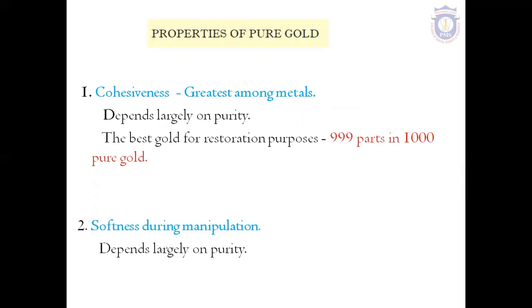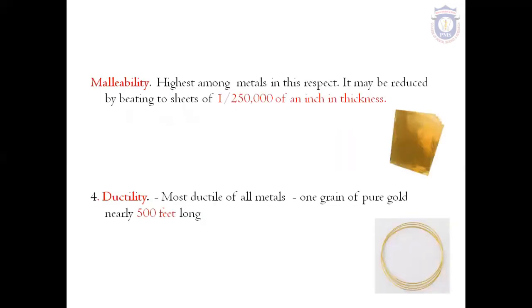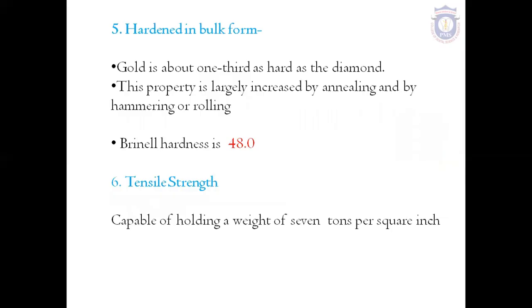The properties of pure gold. Cohesiveness is the greatest among metals. It depends largely on purity, and the best gold for restoration purposes is 999 parts in 1000 parts pure gold. Softness during manipulation again depends largely on the purity. Malleability is the highest among metals, and it can be reduced by beating to sheets of 1 by 250,000 of an inch in thickness. Ductility is again the highest among metals, and 1 grain of pure gold can be pulled nearly 500 feet long. It can be hardened in bulk form.